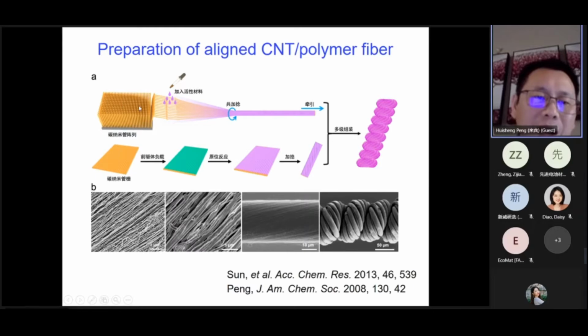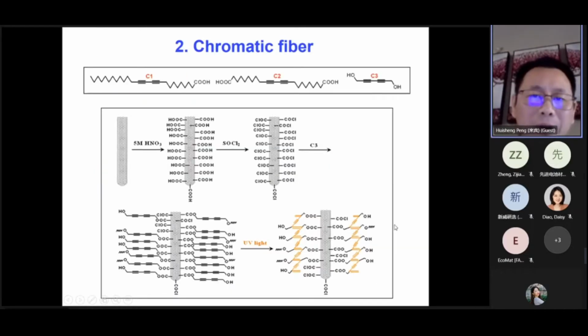We first synthesize a carbon nanotube array, and then we can spin out these carbon nanotubes to form these fibers. During this process, very important, the carbon nanotubes are aligned along the fibers. Of course, this fiber can be further made into these polymer structures, then it can be stretchable. If you look at the SEM imaging, the carbon nanotubes are indeed highly aligned with each other, and this is just the first level fiber that can be further made into these polymer fibers, bigger fibers.